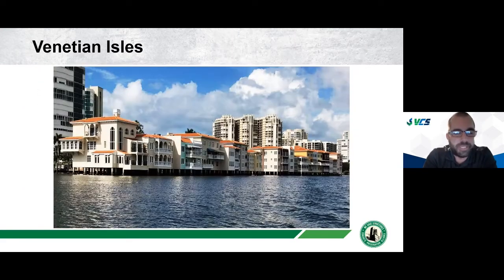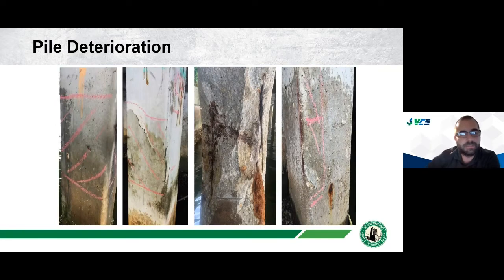Another project that's quite interesting. This is a condominium built out on a bay in Naples, Florida. It's sitting on piles in a bay in Naples, Florida. And as you would expect, piles in a marine environment will start to corrode. So, visual inspection of those piles. Those are just small 14-inch square piles. And you can see we've marked out some delaminations forming. When they've knocked off some of the delaminations, they've lost some strands. These piles only have 4 strands in the 4 corners. And so you can see you have quite significant corrosion activity of the reinforcement already.